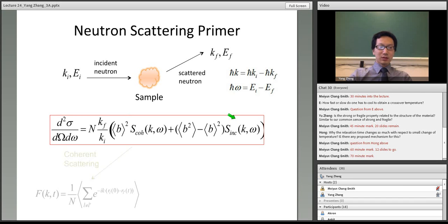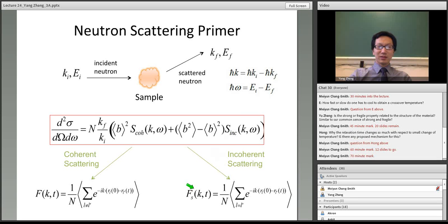The coherent dynamic structure factor is basically a Fourier transform of the coherent intermediate scattering function. The same thing for the incoherent, and that's a Fourier transform of the self-intermediate scattering function. A lot of the theories, especially the mode coupling theory, are based on these intermediate scattering functions. So now you can see why neutron scattering has played and will continue to play a very unique role in the study of liquids. Actually, a lot of pioneers in liquid state physics are neutron scatterers, like Peter Egelstaff.